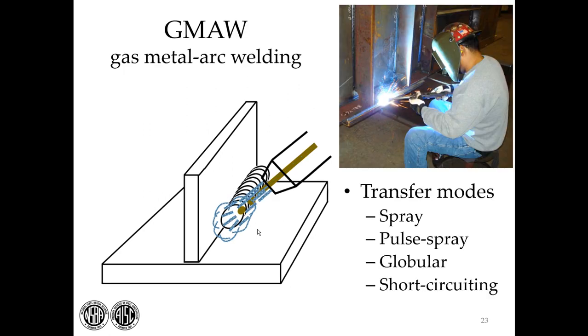The gas metal arc welding is very similar to flux-core, and you have the same kind of delivery, but you'll see there is no flux in the consumable. You see the gas that comes out to shield the arc. One of the key things with gas metal arc welding is the transfer mode. Depending on your electrical settings, there will be a certain mode of transfer when the droplets of weld leave the consumable. They may spray out. You might pulse spray them out. It could be globular or short-circuiting. These are designed to facilitate the type of welding that you do.